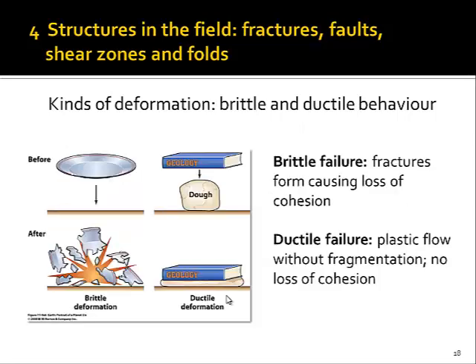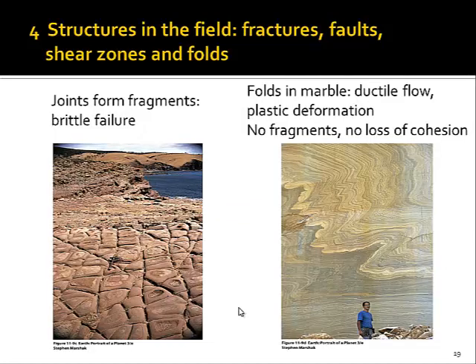This is a way how geologists read information from features in the field. They see a certain behavior and they would say, okay, deformation must have occurred at a certain minimum temperature in order, for instance, to produce these folds that we see here. This is a marble, a layered marble, and here these very beautiful ductile folds, they require a certain minimum temperature to form, and plasticity of marble, of the mineral calcite or dolomite that makes up this rock, will start at 400, maybe 500 degrees to be sufficiently soft to form such deformation patterns.